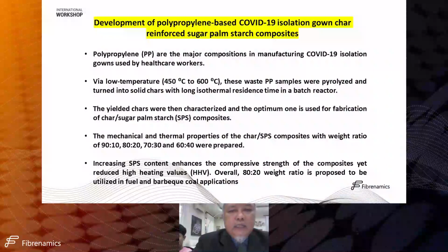The PP is the major composition in manufacturing of COVID-19 isolation gowns used by healthcare workers. With low technology and low temperature, this waste PP sample was pyrolyzed and turned into solid char with long isothermal residence time in a batch reactor. The yielded char was then characterized and optimized, and the optimum one was used for fabrication of the char sugar palm starch composite. The mechanical property, mainly the compressive strength, and thermal property of the char composite were prepared with different weight ratios.